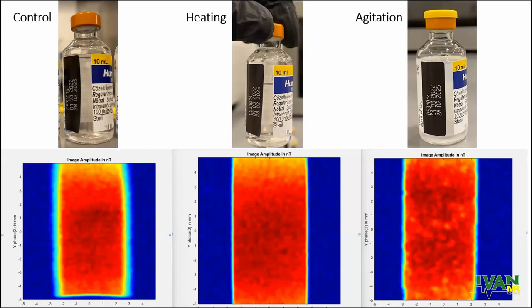This is the MRI results of our experiments. This is the control. This is heating and agitation samples. As you can see, there is no difference between control and heating sample. We cannot detect any color change or any aggregation by naked eye. However, with the MRI image intensity, we can see the differences. So MRI can be a quick tool to detect quality problems. In the agitation and the control samples, we can see the color change by eye, and the MRI image intensity differences also show the extreme case.